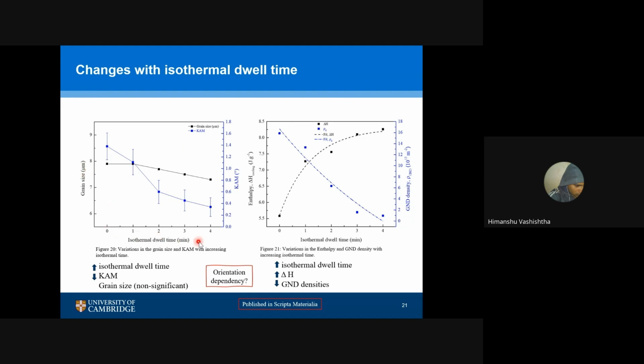Some grain size has been measured with isothermal dwell time. Not too much change was there. I showed you the CAM map as well, and here is the numeric calculation. For the 0 minute case, the as-received plate, there was too much CAM value, kernel average misorientation, and when heating it, it's turning drastically. So grain size has not changed too much, so we can claim whatever changes we are getting are because of dislocations only, not because of grain size, although the grain size is changing fractionally and insignificantly, from 7.75 to, let's say, 7.5 or even less.